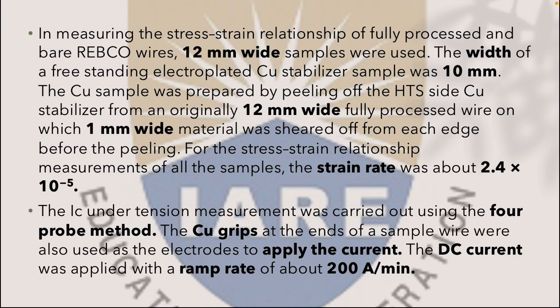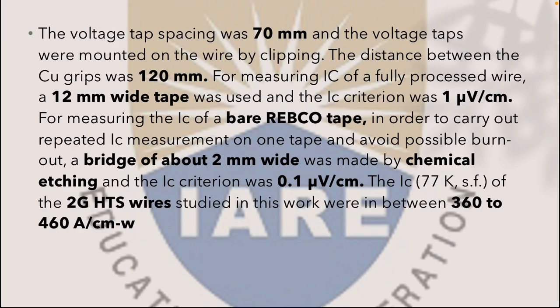In measuring the stress strain, the Ic under tension measurement was carried out using the 4 probe method. The copper grips at the end of the sample wire were also used as electrodes to apply the current. The DC current was applied with a ramp rate of about 200 amps per minute. The voltage tap spacing was 70 mm and the voltage taps were mounted on the wire by clipping. The distance between the copper grips was 120 mm. For measuring Ic of a fully processed wire, a 12 mm wide tape was used and the Ic criterion was 1 μV per centimeter.